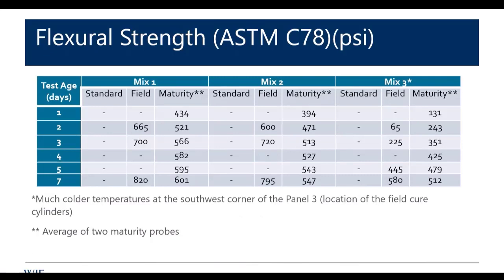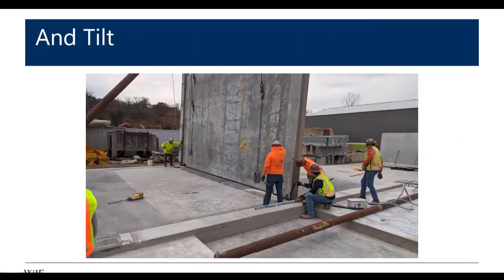Basically, the bottom line is that it was really cold, and where the cylinders were placed to cure for the mix 3 was a very cold, exposed part. So those test cylinders never got any heat, and they died. And it didn't happen in the slab. But we were able to tilt all the panels. They all went up, and it was widely viewed as very successful.